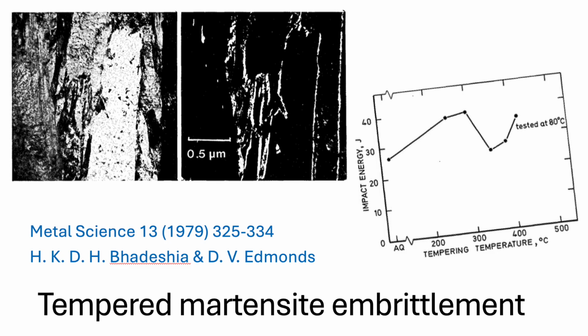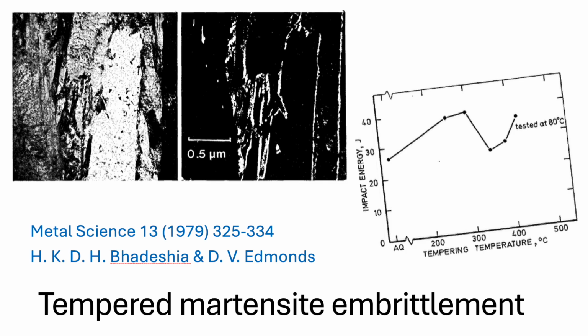You're constantly balancing these competing instabilities. How so? Well, you might add an element like molybdenum because you need certain properties it provides, maybe high temperature strength or hardenability. But that same element might also inadvertently increase the stability of retained austenite, making sure that RA sticks around long enough to decompose right in that critical 300 C tempering range, precisely where you least want that reaction to happen. You solve one problem and potentially create another. That's the game in materials science a lot of the time.